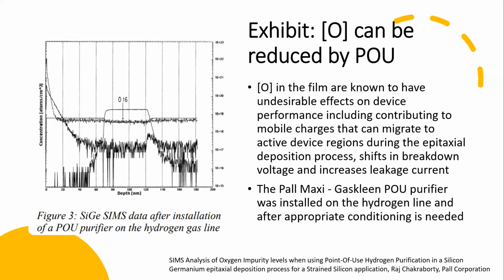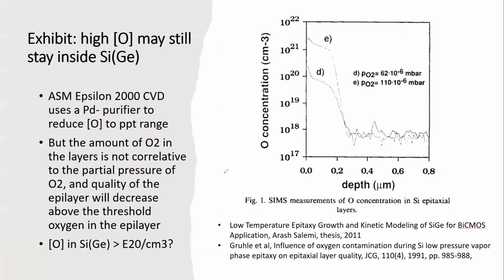So you put some filters on and say, okay, my incoming hydrogen line is purified. But don't forget, your chamber needs to be clean too. It's not just the incoming line. You just clean the hydrogen line, but there are other gases you're using, right? You have silane, which, of course, you're not going to put a purifier on, but the chamber itself is kind of dirty to some extent. You try to make it as clean as possible. So that's why you change your PM frequency to make sure it's clean. And people study that, right?